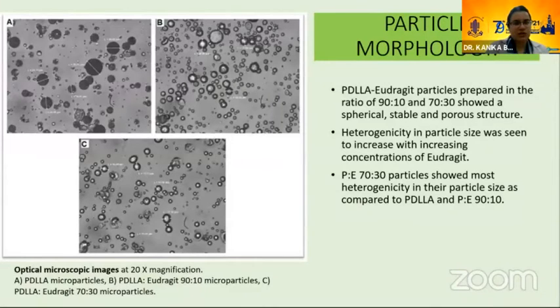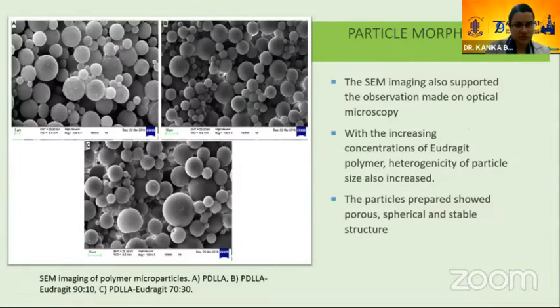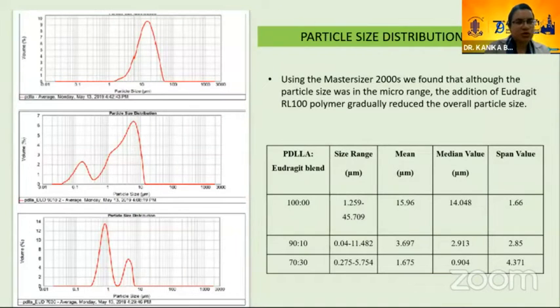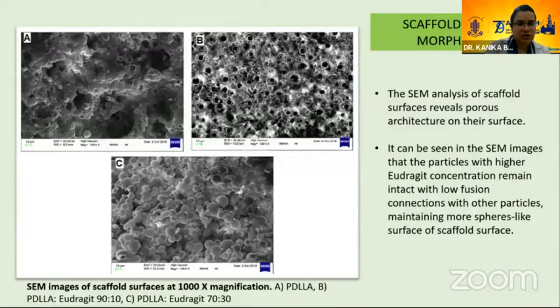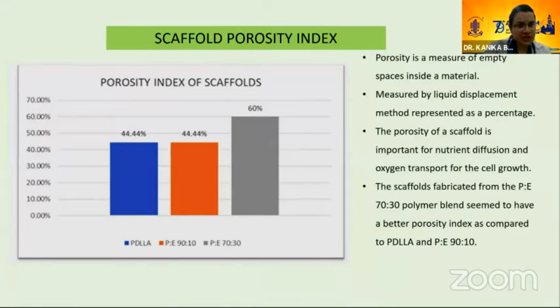Coming to my results, the polymer microparticles that we formed were stable and spherical, and the heterogeneity in size increased as the Eudragit concentration was increased. The same was confirmed on scanning electron microscopy also. The size distribution of the particles was in the micro range, and they were uniformly distributed. But with the Eudragit, the size was smaller. Coming to the scaffold, on scanning electron microscopy we could see that they had a porous structure, which is good for cell growth. And the porosity index was also measured.